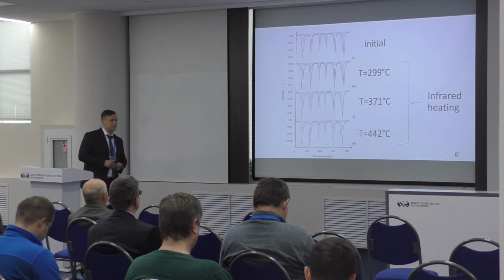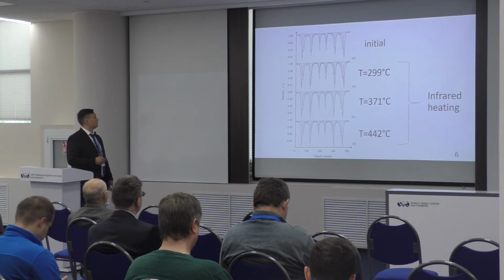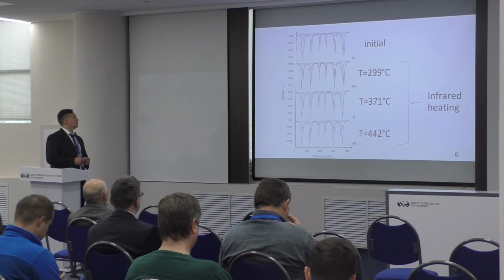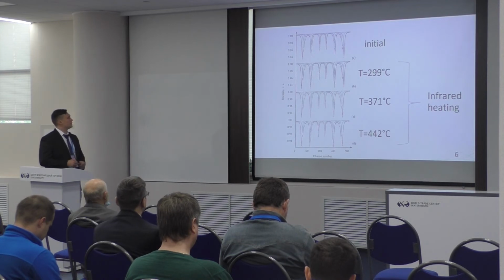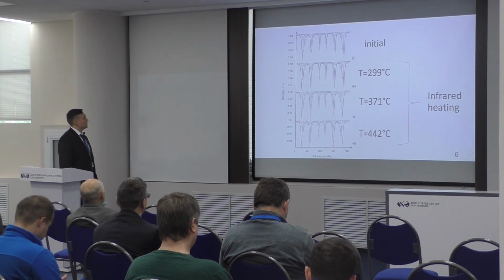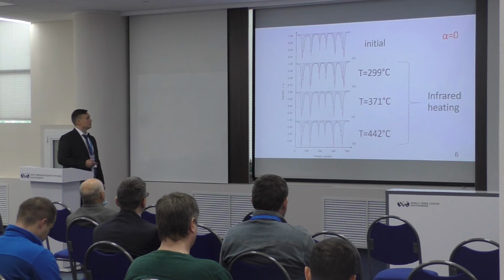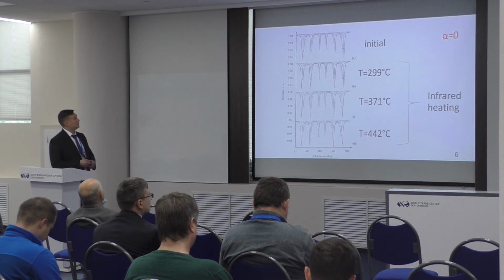Now let's talk about our data. There is the spectrum of the initial sample, and three spectra of the heated specimens up to different temperatures. There is no singlet in the center of the spectra. It means that there is no gamma phase or FCC lattice in these samples. And we calculated the alpha parameter. It is equal to 0 for each spectrum.